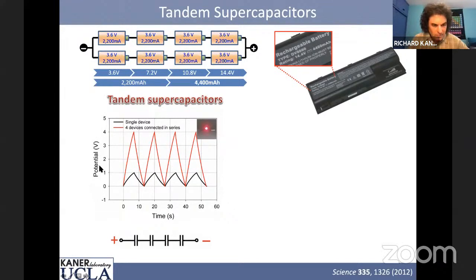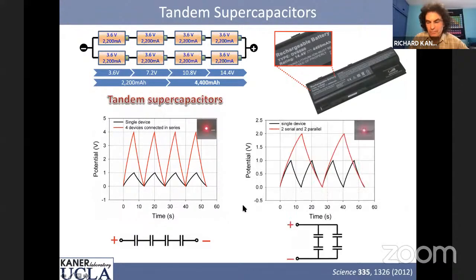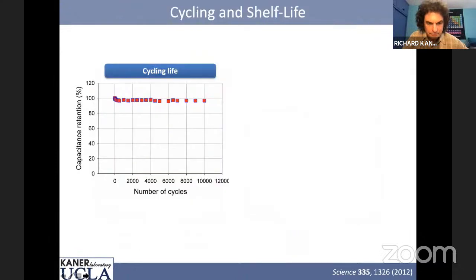So here's potential versus time. A 1 volt device, we put 4 of them in series, we get out 4 volts. If we put 2 in series and 2 in parallel, we double the voltage from 1 to 2 volts, we double the area under the curve. So simply by stacking these devices together in series and parallel, you can get out any voltage you want. You can get out any current with enough of these things. So this is a good way to build devices.